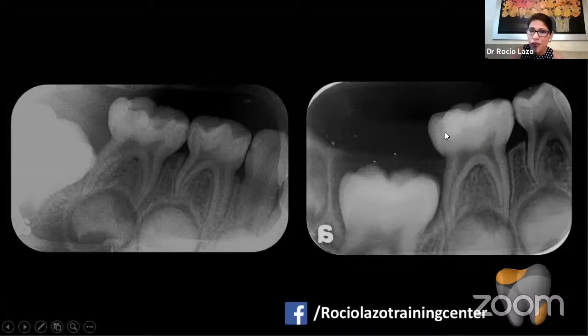Look here, it's sealing perfectly. It's not the same as what happens with the resin. In the resin, the problem is that metalloproteinases are going to degrade the adhesion. And here we are not going to have problems with the metalloproteinases, and we are going to have great results.